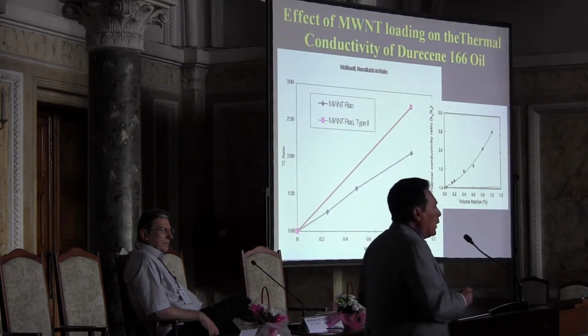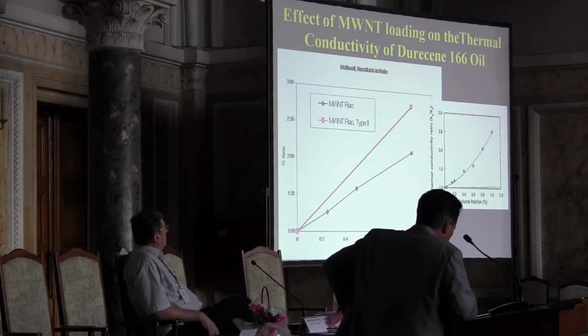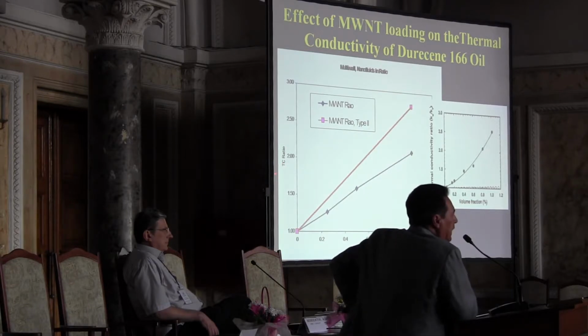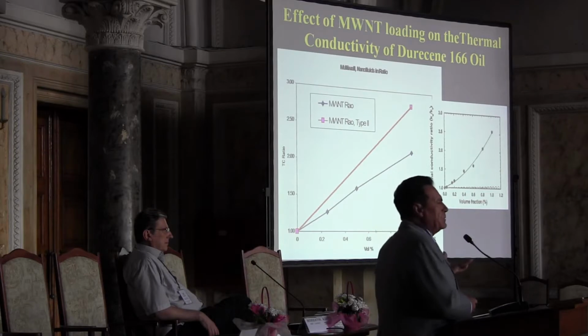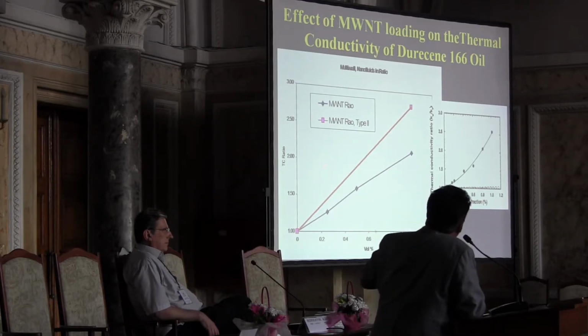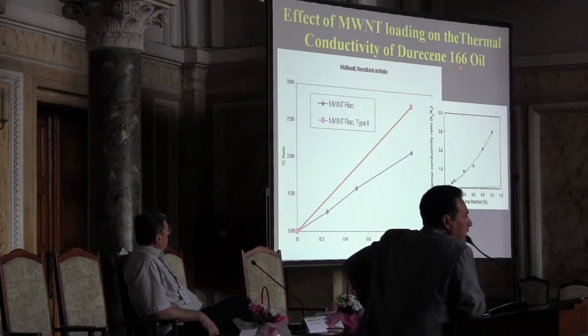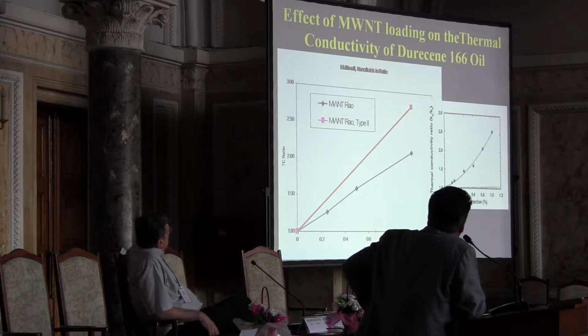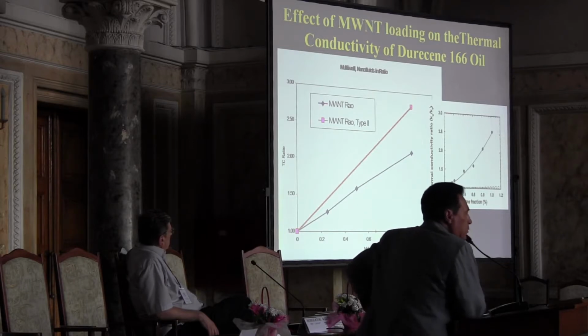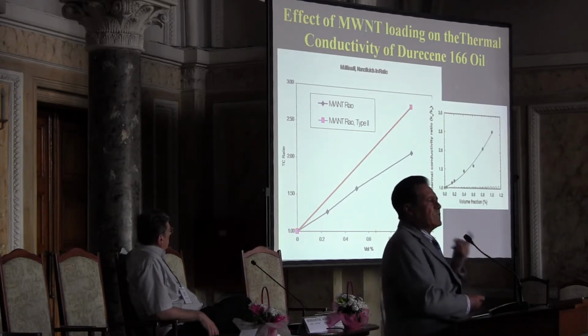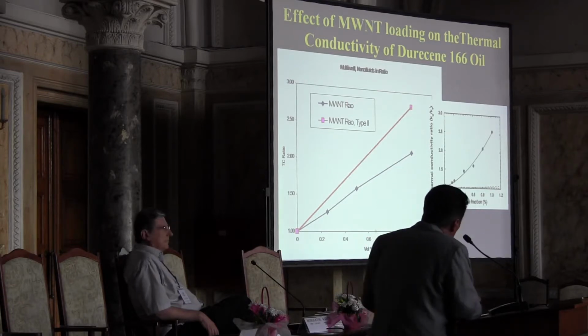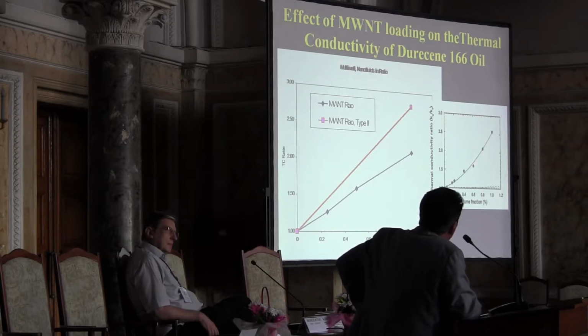And if you are looking at these results, these are our results that you are having in here. And these carbon nanotubes were prepared for us by one of our colleagues from Clemson, okay? And here what you are seeing is the thermal conductivity ratio. So this is the thermal conductivity of the nanofluid divided by the thermal conductivity of the base material, that in this particular case is Durecene 166 oil. So you are talking about, say for instance, for 1 volume percent loading, a thermal conductivity ratio of 2.75. That means that you have an increment of 175% in the thermal conductivity. And these results are similar to the ones that were obtained in our Argonne laboratory. Okay.